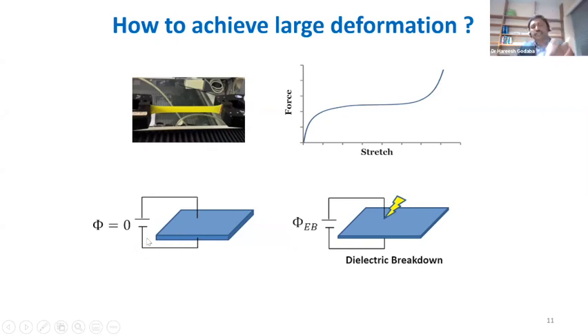Now we could imagine trying to do something very similar, but by using electric field. As I mentioned in the discussion earlier, when we have an electric voltage across the two compliant electrodes, a stress is generated in the areal direction that will basically pull the membrane. So we could try to achieve something similar. And then the failure mode is basically once the electric field is very large, there is a dielectric breakdown, which is similar to the breakdown of air during arc welding. So we can have similar dielectric breakdown in these polymers or in these elastomers.